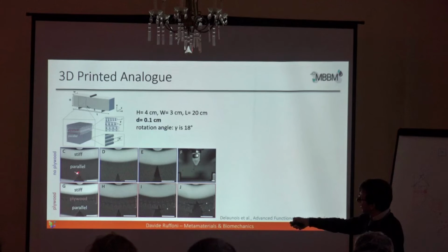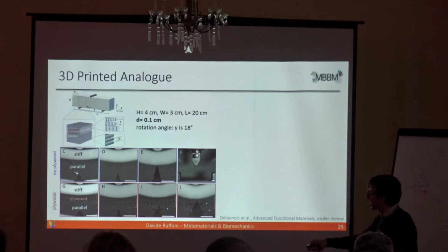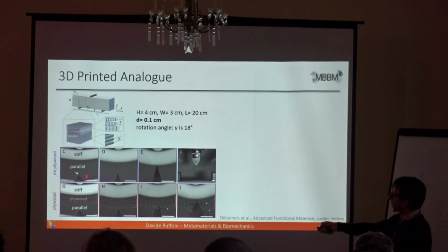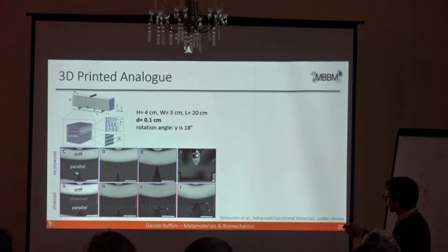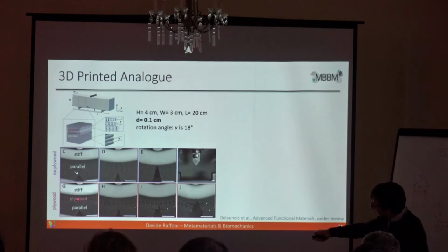And what we see is that damage propagates very straight, as expected, because there are all parallel fibers, so there are no crack stopping mechanisms. And when it reaches the hard material, the sample just exploded, let's say, and splashed away from the machine. And in the second design configuration, we added a plywood.